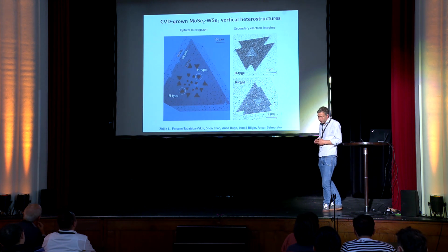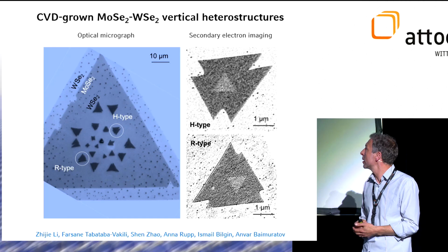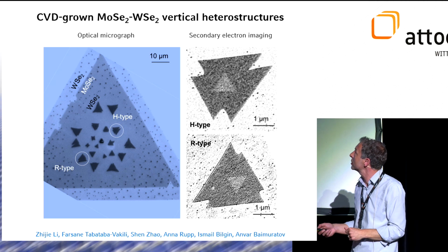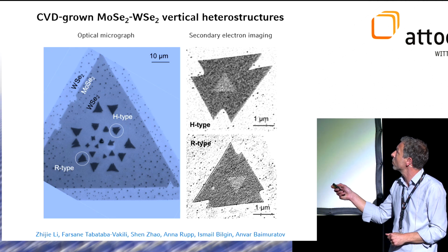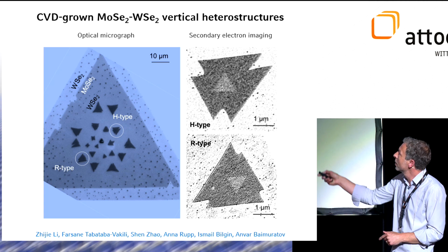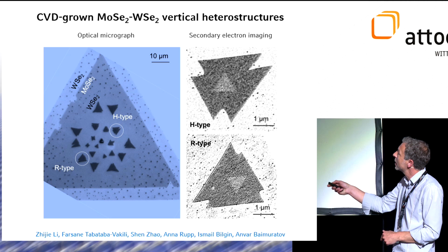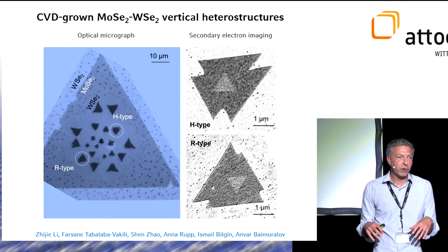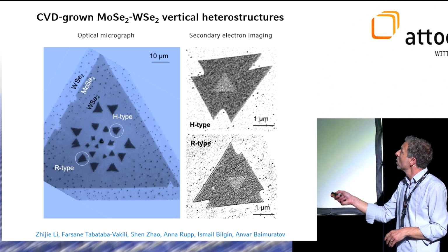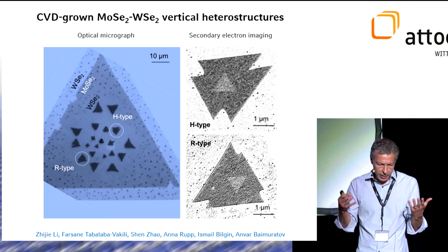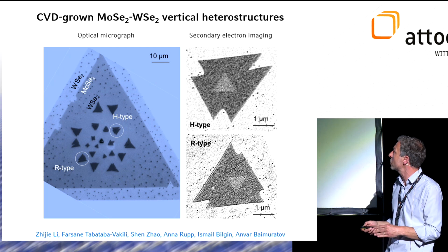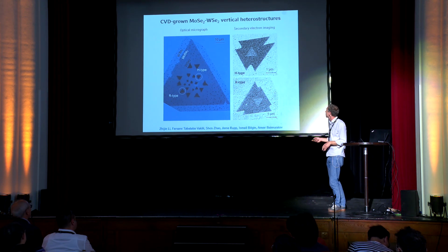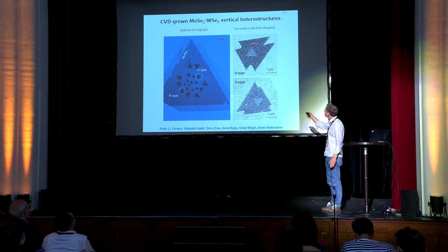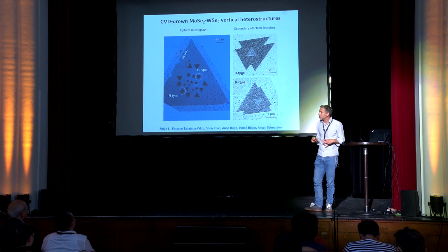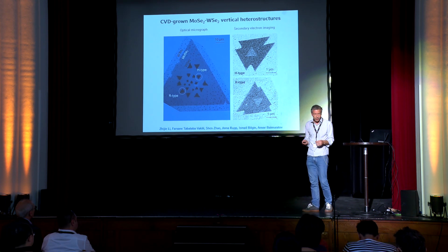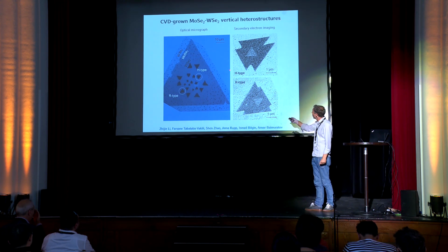So with this insight, since we also do chemical vapor deposition of such crystals, and in particular this one is a vertical heterostructure of tungsten diselenide grown on molybdenum diselenide. You see that the outer large flake here is molybdenum diselenide, and on top we see tungsten diselenide islands emerging in both H and R type configurations, but also other twist angles I will not comment upon. So the question is, what do we find now with this notion of reconstruction on our mind in such CVD-grown vertical heterostacks? In secondary electron imaging, typically in CVD growth you obtain very nice triangular monolayer crystals. The triangles are already distorted at the heterobilayer level, both for H and R type.